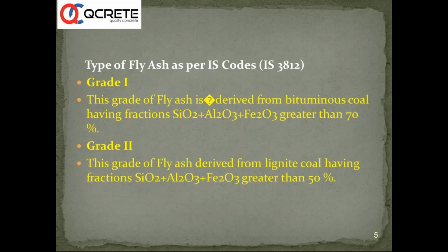So before we move into our experience, as I said, we are going to talk for some time on different grades of fly ash, kinds of fly ash, and some of the benefits that we get from fly ash. As a part of that, we are talking about grade 1 and grade 2 fly ashes as per our code IS 3812. Grade 1 is where SiO2 plus Al2O3 plus Fe2O3 is greater than 70%. Grade 2 comes from lignite coal, and it has SiO2, Al2O3, Fe2O3 greater than 50%. We need to remember this SiO2, Al2O3 plus Fe2O3 is the major component, and this is the active component which makes this SCM very popular.